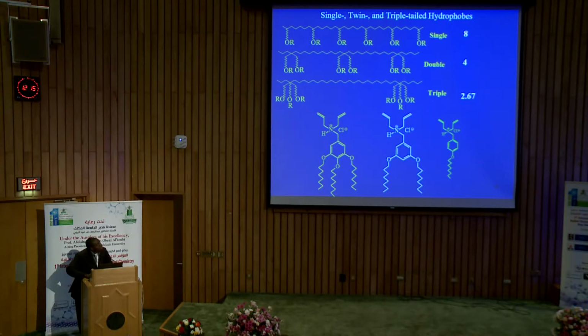For example, we have 8 moles of single-tail that is equivalent to 4 moles of double-tail, and it's equivalent to 2.67 moles of triple-tail, just to have a meaningful assessment of the hydrophobic properties of these polymers. We also synthesize another set, 12 moles of single, 6 moles of double, and 4 moles of triple. They all contain the same moles of the hydrophobe, but of course differently arranged. So we also have the next one. The first one we couldn't because it's insoluble in water, and we take the double tail, which is 8 moles, and then the triple tail, which is 5.33 moles. So in order to investigate this exciting proposition, we decided to synthesize this particular monomer.